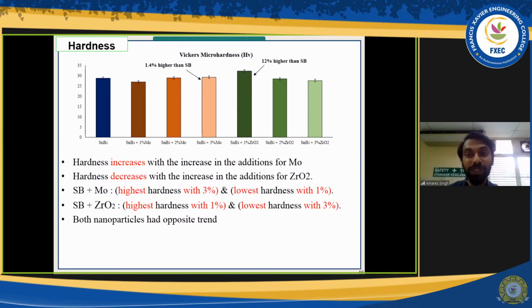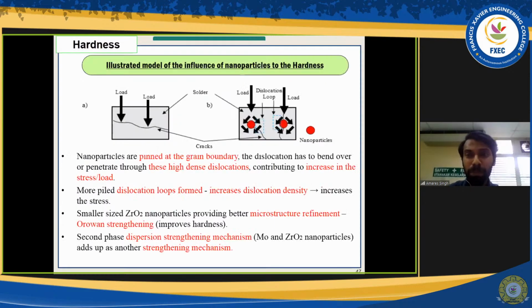But then some nanoparticles which did not go to the interfacial layer stay at the solder area, on the solder side. So they act as a second phase dispersion strengthening mechanism that increases the hardness. So it was quite obvious for the 1% zirconia and 3% molybdenum. So what actually happens and how do the nanoparticles impede or restrict the dislocations? We can see here that the red highlighted dots or rounds are the nanoparticles. Upon load, upon penetration, the load can't break the nanoparticles because they are small in size and at the same time, they are very hard.